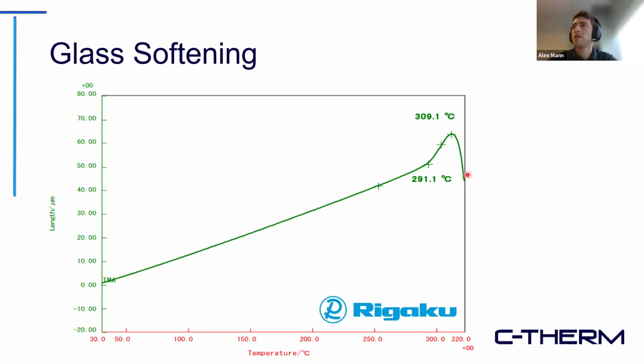This is actually the dilatometric softening point, and it's less of a material property, more of an artifact of the methodology. As you may recall, the sample sits on the support tube and the detection rod is on top. It pushes down on it, applying a small force, 1 to 1,000 millinewtons. Eventually the sample will reach a point where it can no longer support the force applied by the detection rod, and the rod will actually begin to penetrate the sample. So in reality, the sample isn't shrinking. This is just what the machine sees.